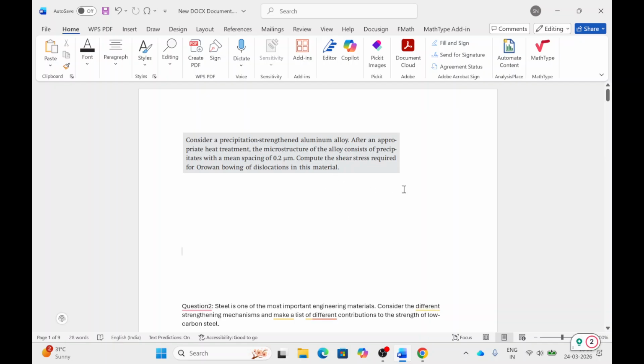The first question: consider a precipitation strengthened aluminum alloy. After an appropriate heat treatment, the microstructure of the alloy consists of precipitates with a mean spacing of 0.2 micron. Compute the shear stress required for Orowan bowing of dislocations in this material. So there are two cases: when the dislocation shears or cuts the material, or otherwise the dislocation bows around the precipitate particles.